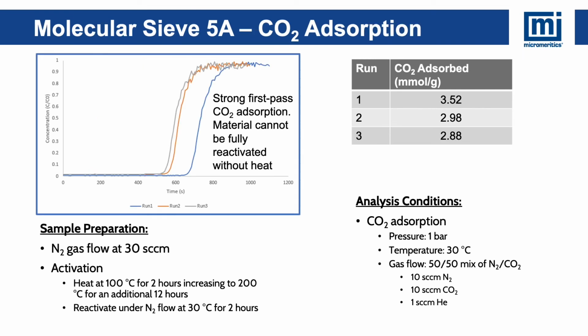Next up, looking at molecular sieve 5A, we see a much larger decrease in capacity between runs 1 and 2, and then a little bit more consistent between runs 2 and 3. Showing strong first pass CO2 adsorption, however, the material cannot be fully reactivated without heat. Additionally, this material adsorbed the most CO2 of all the materials we measured during this study.